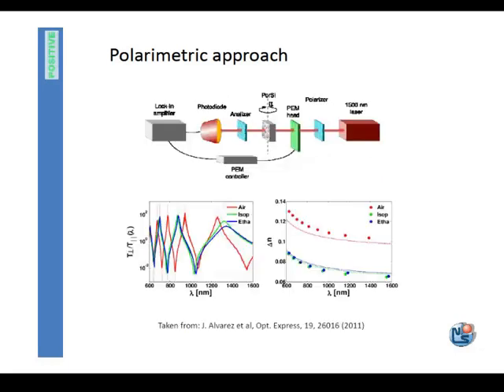effect. So our colleague in Valencia built up an optical setup. There's a tunable laser source, a polarizer. This is a photoelastic modulator that sinusoidally varies the polarization of the light. The porous silicon sample is placed in between. And if you do a wavelength scan in this type of experiment, you get such an interferogram, and you see that if you have air, isopropanol, or ethanol in the pores, you see different interferograms.